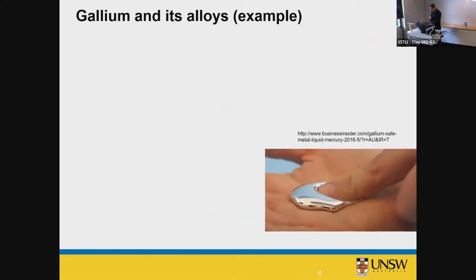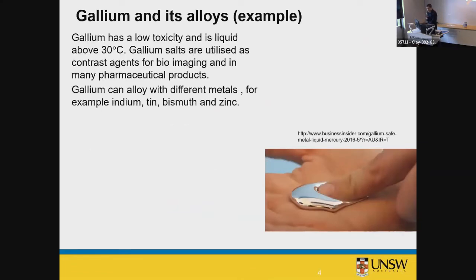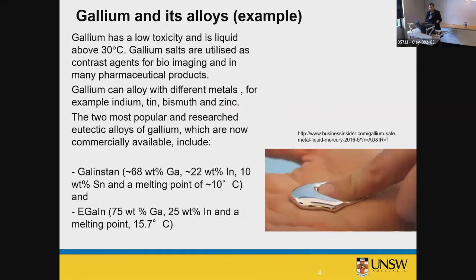Now, the representative of this group is gallium, melting point 30 degrees. It's safe. It can alloy with zinc, bismuth, tin, indium at high concentration, and it makes very fascinating alloys. For instance, EGaIn, 75% gallium, 25% indium, the melting point is 15.7 degrees. So it's a good rival for hazardous mercury because you can use it at room temperature as a liquid metal.